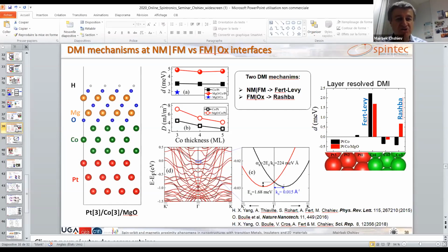That change was also related to the position, because at that time we were using Friedel sum rules to calculate the spin Hall angle. Really, the filling and position of the impurity states in respect to the Fermi level of the host was defining the sign of the spin Hall angle. So from that point of view, obviously there is a similarity and there might be some correlation. However, I can answer more affirmatively regarding the Rashba-induced DMI, which I gave you an example of.